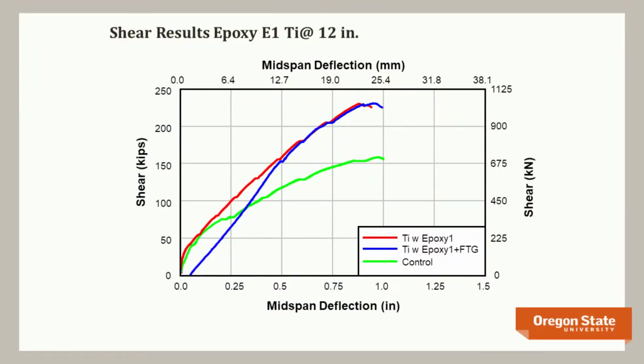Here's the load deformation response. A control specimen shown in green. The red specimen is if we just put it on the lab floor and test it, we can get an additional, almost 100 kips out of this thing. That's per girder, right? Typical bridges are 4 girder lines, so you can see you can get significant strength increases. The blue line here is our fatigue and freeze thaw, and then we put it on the strong floor to test it to failure. And you can see we get the same behavior and the same strength out, even if we bounce it up and down before we test it to failure. So we see no environmental durability problems.